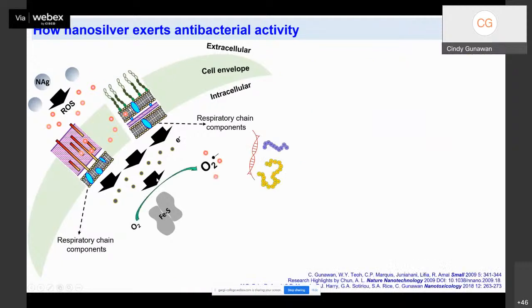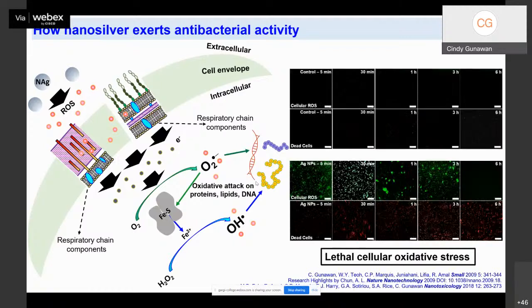So these electrons then react with molecular oxygen to produce the reactive superoxide radicals. And these superoxide radicals can in turn attack the iron-sulfur clusters in proteins, releasing the Fenton-active Fe2+, and this Fe2+ can then react with cellular hydrogen peroxide to produce the highly damaging hydroxyl radicals. So this formation of cellular reactive oxygen species, or ROS, can then cause oxidative damage on proteins, lipids, and DNA. So, cellular studies show these cellular ROS generations in bacteria.